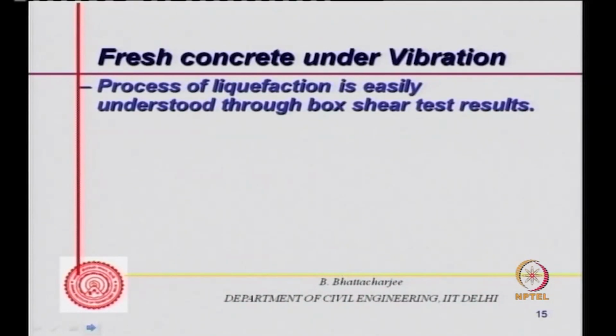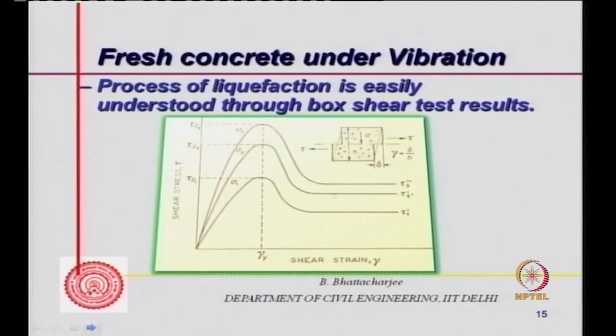The process of liquefaction is easily understood through, let us say, the box shear test, which we normally do in soil. Now, this kind of test was also conducted on concrete long back, and one would see something of this kind. For example, you have shear strain along this direction and shear stress along this direction. Now you apply normal pressure, sigma n, and tau is applied from this side and strain is measured, delta divided by h. This is h and delta is this distance. So if you measure the stress versus strain, you find this sort of curve, and this depends upon sigma 1, sigma 2.